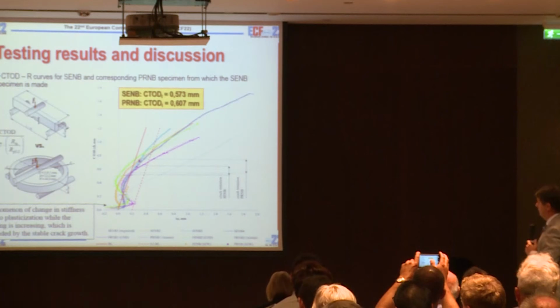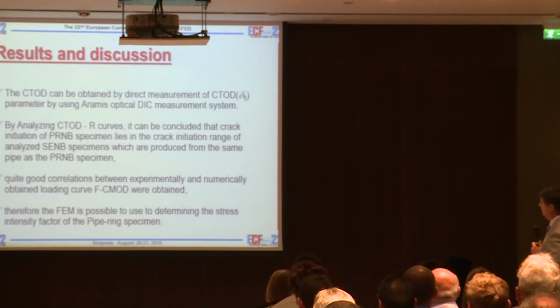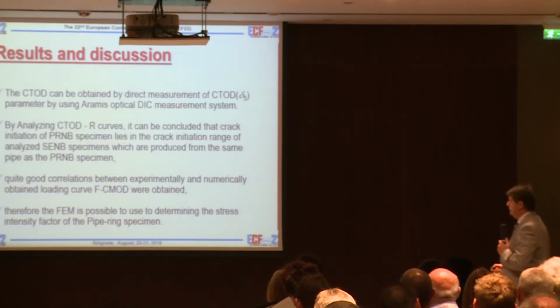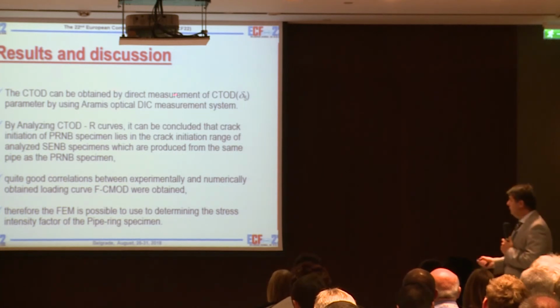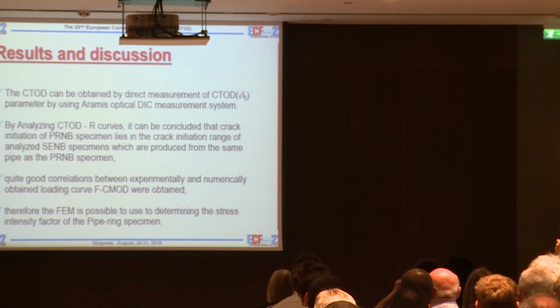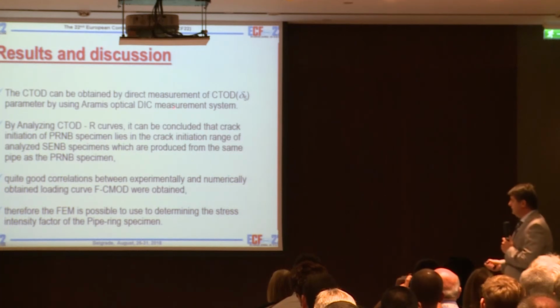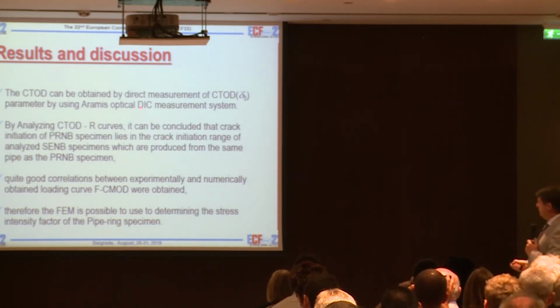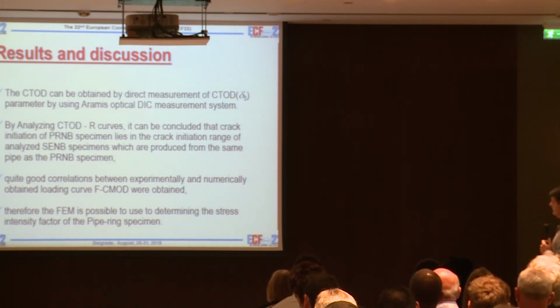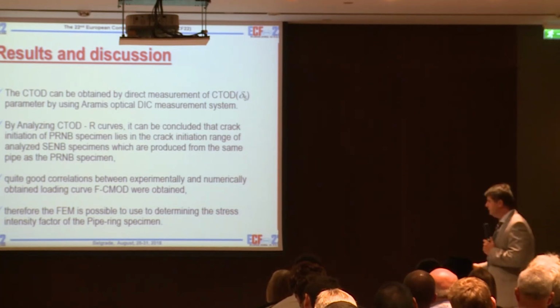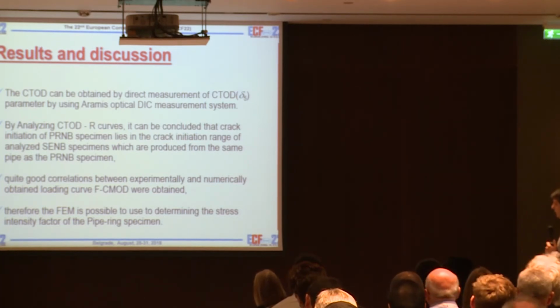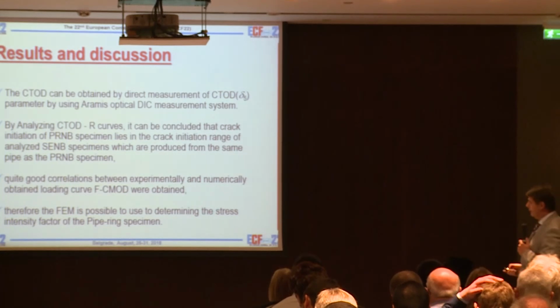So now we can say that CTOD can be obtained directly by measuring CTOD delta 5, and as I said, by using the Aramis, DIC or some digital image correlation measurement system. And also we see that we have quite similar curves, and also in quite a near area of crack initiation.